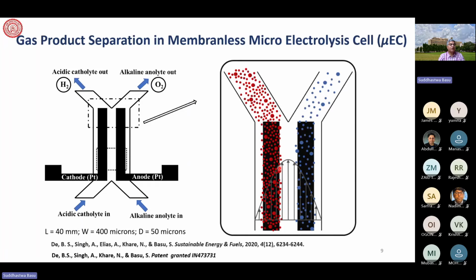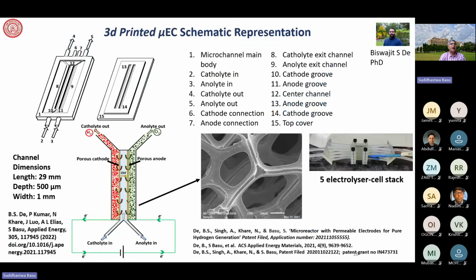Okay, so that was our patent, and that was our publication, where we use asymmetric electrolyte, and the voltage requirement we brought down to about 0.8 volt. In this case, the requirement is 1.23 volt otherwise, which is the standard potential for water splitting in either acid or alkaline medium. But because of the use of the liquid junction potential, we could improve the efficiency by a huge amount. And this design that we have proposed is the best among the other designs that I just presented or people have come across.